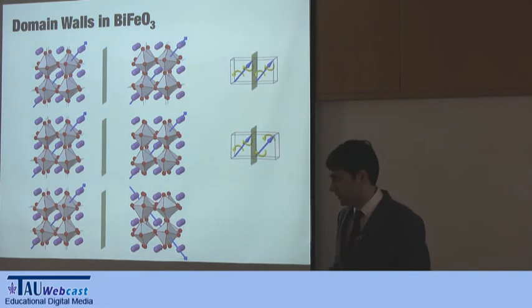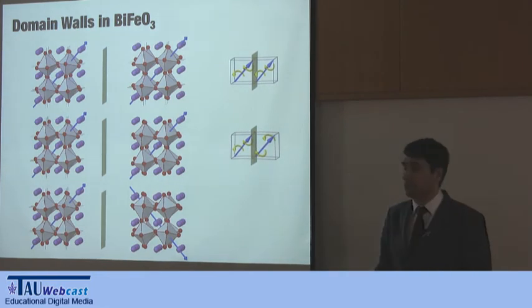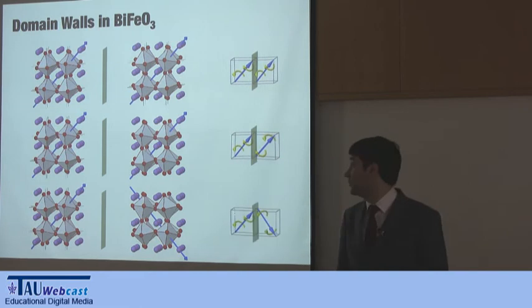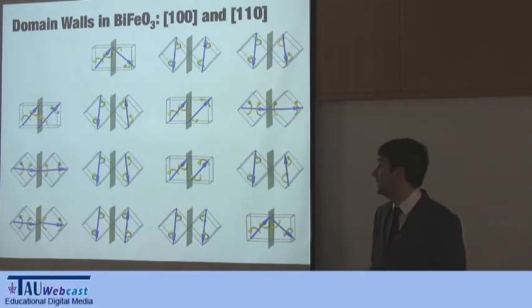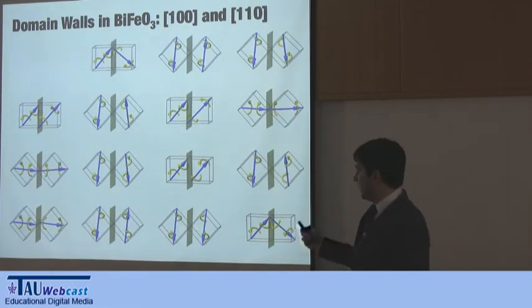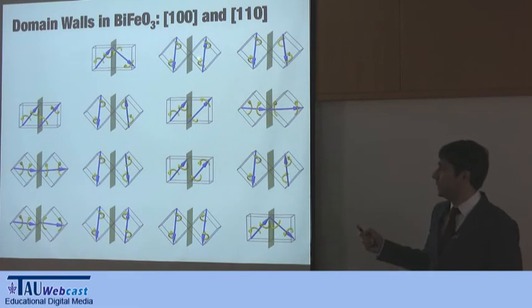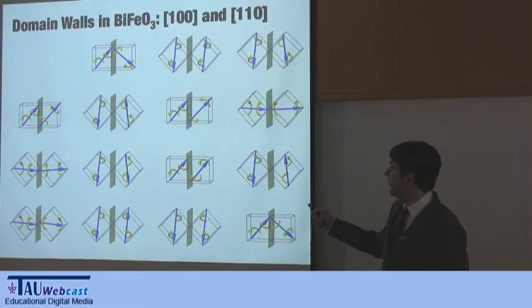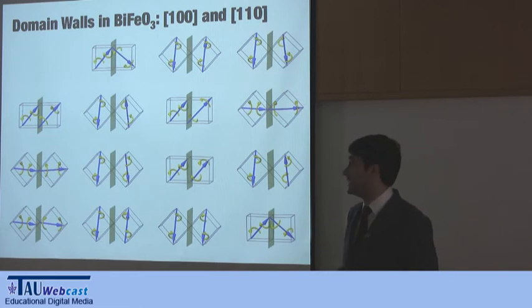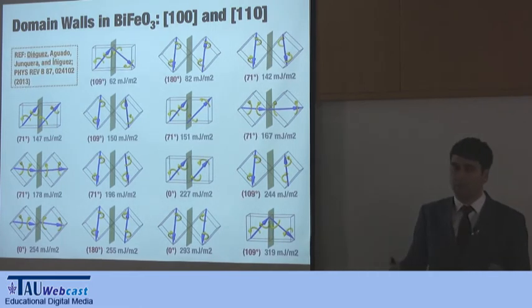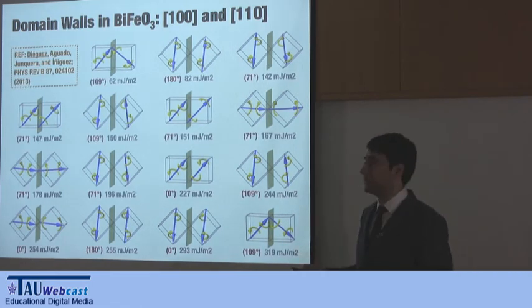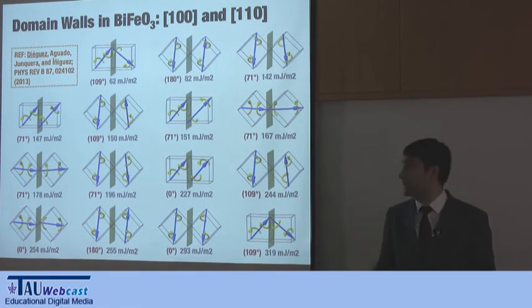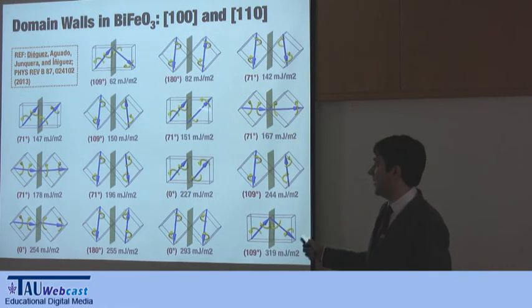So like this one. Okay. So you have to see how many combinations you get, and you have to find the energy of them and try to learn from the pattern that you find. If you bother to do them all for the 1-0-0 direction of the domain wall or for the 1-1-0, you end up with a set of them. You can compute the energies to form any of these domain walls, and then you can see what patterns arise here.